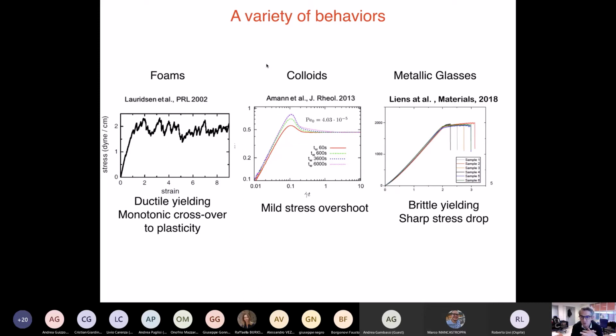Then in the middle of this slide, you have the behavior of colloids. These are, again, experiments. In the stress-strain curve, sigma versus gamma, you see an overshoot. Sigma goes around a maximum, and then it goes down to a plateau value. The plateau value is the value of sigma at which the system is just flowing. This is a behavior which is a bit different from that of foams, and intermediate with respect to the behavior that you find in metallic glasses.